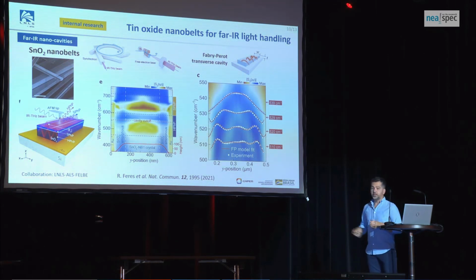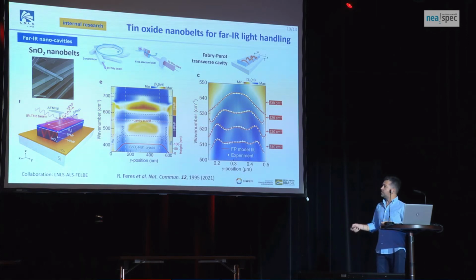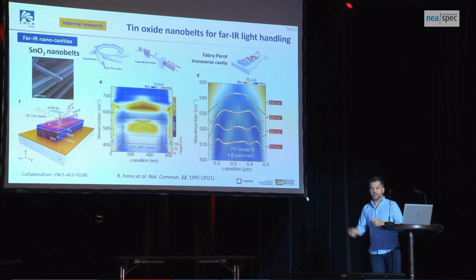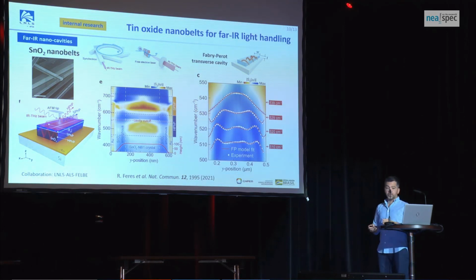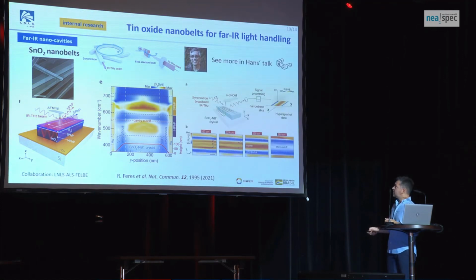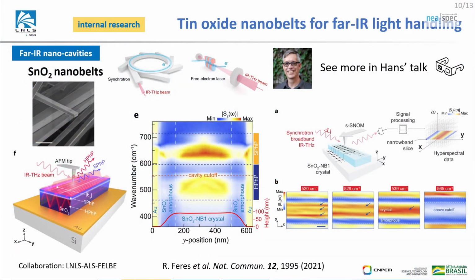We could not test the waveguide modes just because they are too long, and also the shape of the end of these nanobelts is not so well defined. So it's very hard to have a nice reflectivity there. We also took some hyperspectral imaging just to confirm those oscillations, still using the synchrotron, and we could see nicely the different oscillation peaks, different modes here, and also that above the cutoff frequency for the cavity, we don't see any mode inside.